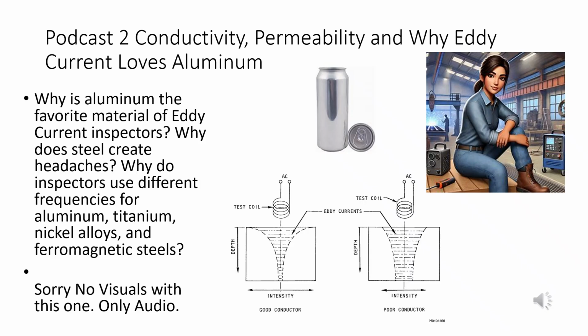Life is good. Why did aerospace fall in love with ET? Think about the typical aircraft inspection: aluminum skin, fastener holes, lap joints, fatigue cracks, stress corrosion cracking, all near the surface, all highly conductive material, all non-ferromagnetic. That's basically a dream scenario for ET.